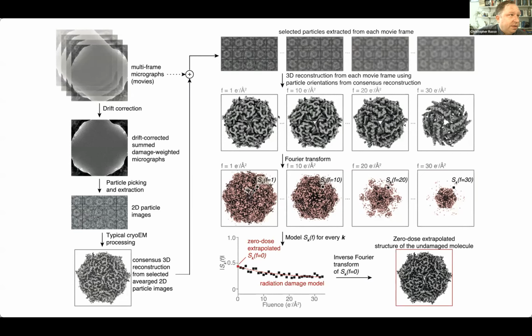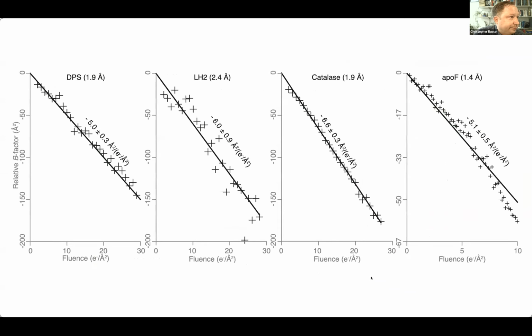So these are the real space maps here in gray. And you can see the radiation damage kicking in here, right? This first map is the best, and it gets worse and worse until a lot of the high resolution features are cooked away. And this is the equivalent Fourier space representation of it. So this is what you see in Fourier space. This is this exponential decay. And you then go in this Fourier space map and fit every single one of these voxels, or these structure factors, individually, and extrapolate them back to 0 dose. And so the final map is just a single map that's calculated from this series of maps.